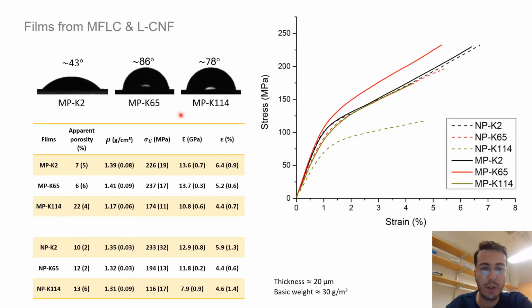Here you can see water contact angle on the micropapers with K2, K65, and K114. You can see for higher kappa we have larger water contact angle, and it shows that this is because of lignin character, which makes high K films less hydrophilic.